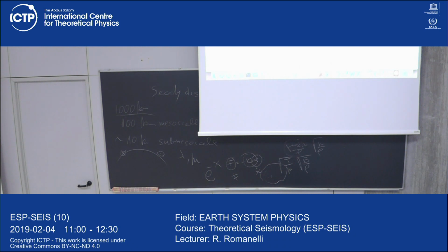Can be very low, but not lower than some tens. Also for a sedimentary layer. Maybe the extreme is something like mud, but it has a Q of 10. It's not 1. It's not strongly damped. On average, if you take this vision as an integral, if you measure on the top with free modes or surface waves, it's 100 for many frequencies. Absorption band, SLS can be used to describe all of them, but constant Q gives us also dispersion. That's the summary of all this pack of slides.